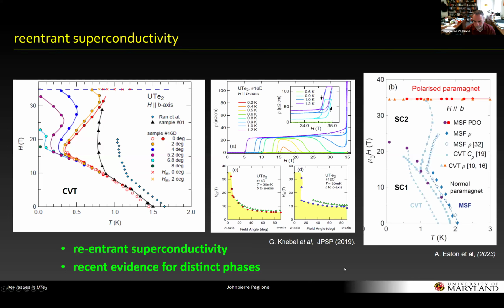All right, so moving on, reentrant superconductivity was observed also very early on, and so we kind of saw it in our first experiments with upper critical field, just going up to the highest fields we could measure in the lab. And then quickly followed up by the Grenoble group, where they actually saw, if they tilted the field a little bit away, they could see this reentrant behavior for fields along the b-axis. And of course, this has evolved with higher TC samples and more elaborate phase diagrams. But at the time, this was sort of the most interesting thing, that there was a reentrant phase that pointed to a second superconducting phase at high field that was abruptly cut off by this field polarized phase, which is a first order transition. You can see some of the raw data here, the first order transition.